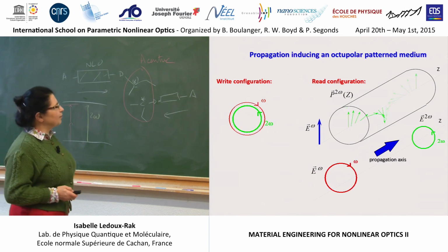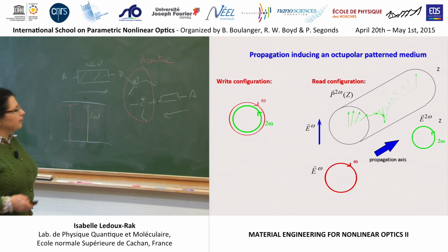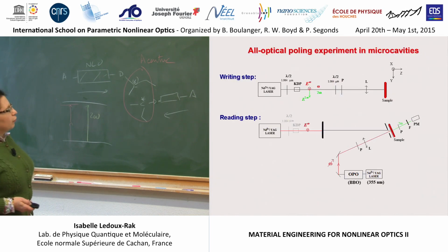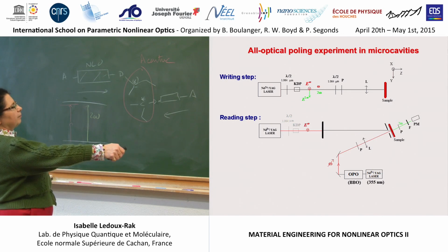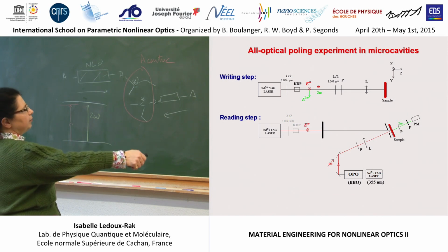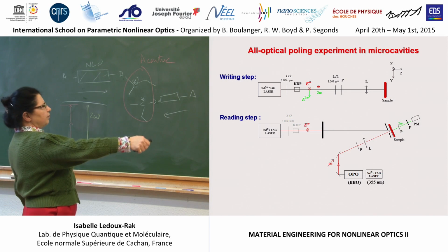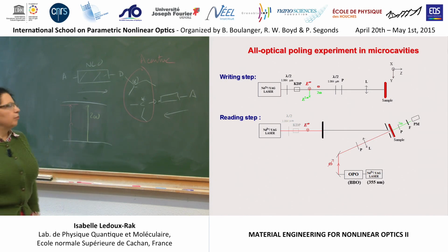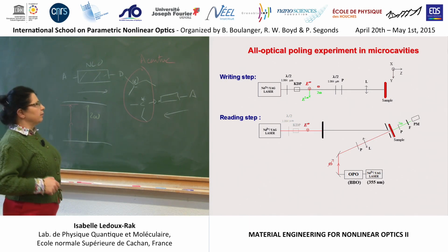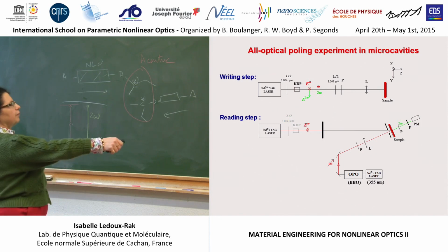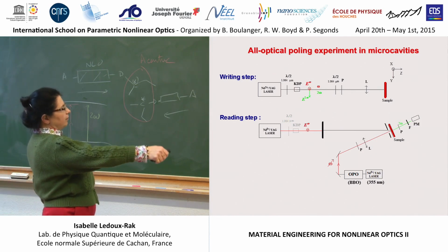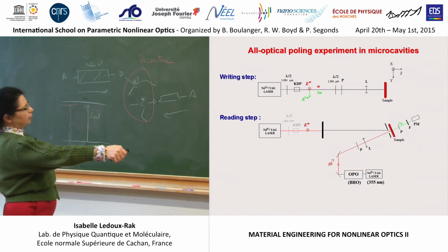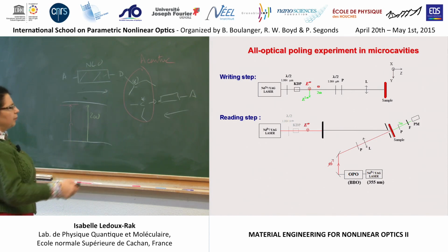So we have to find some other tricks to overcome this point. Optical poling can be made very simply by mixing some omega and 2 omega beams. Usually the intensity at 2 omega must not be too high. Only a small intensity is required for performing the photoisomerization. And we can control the polarization state by using a proper polarizer.